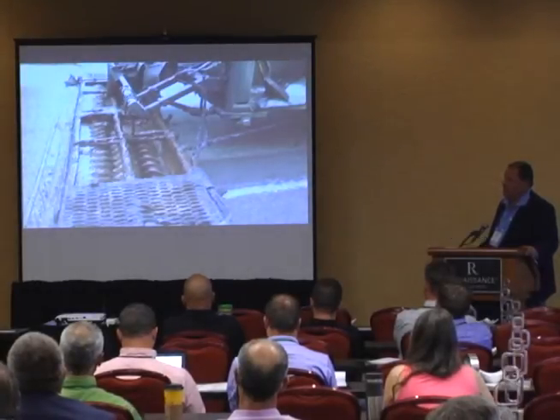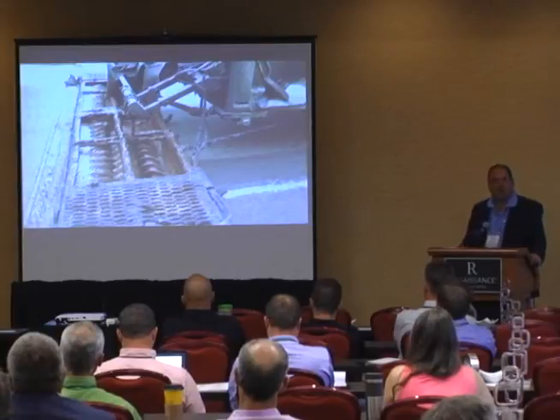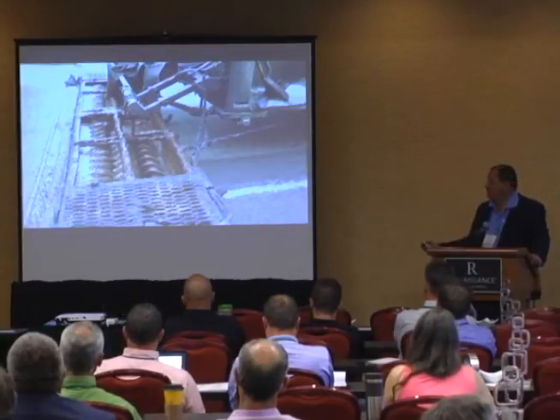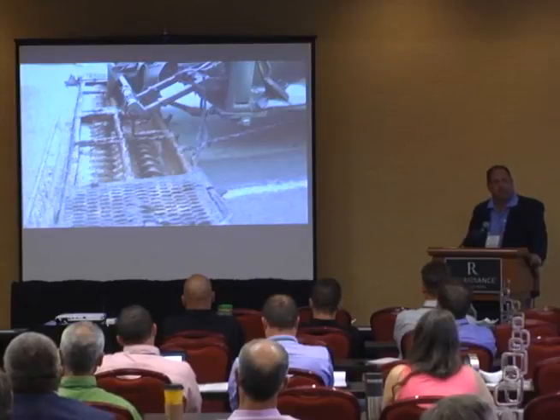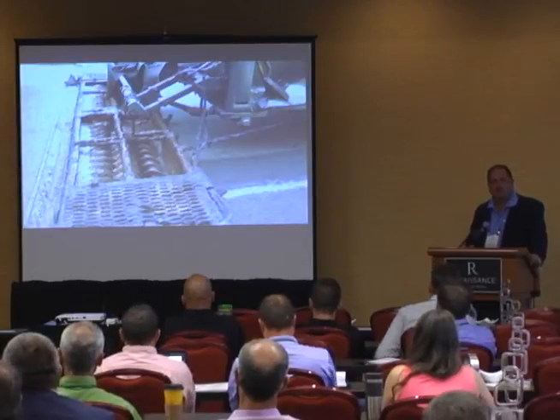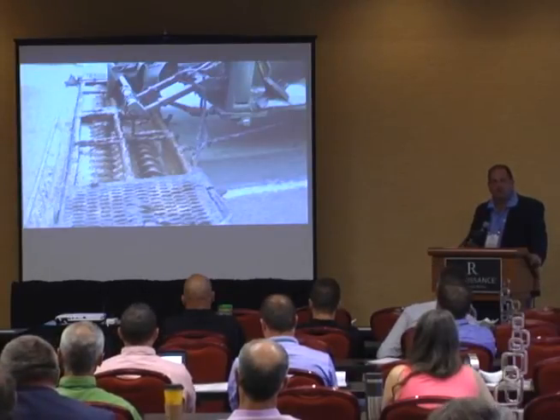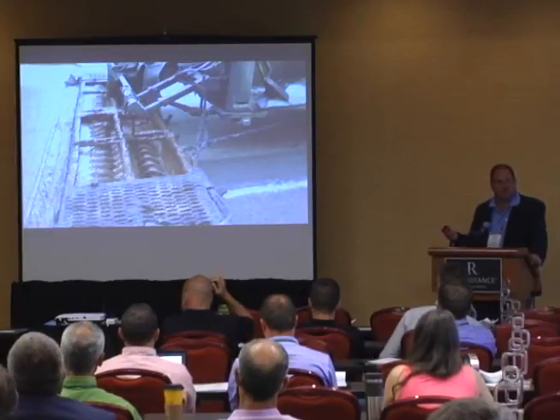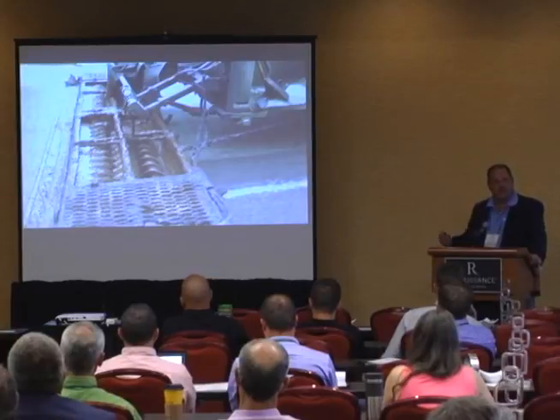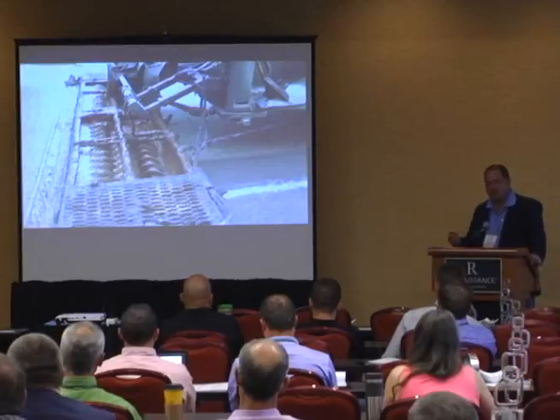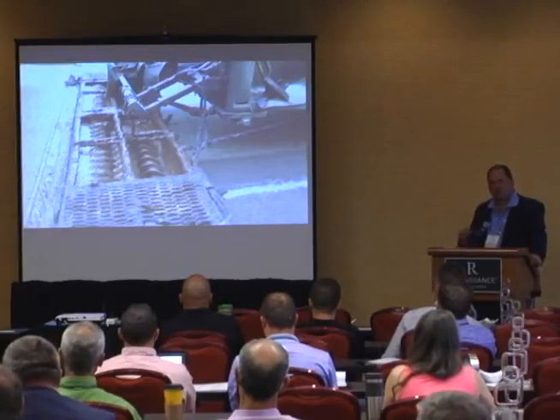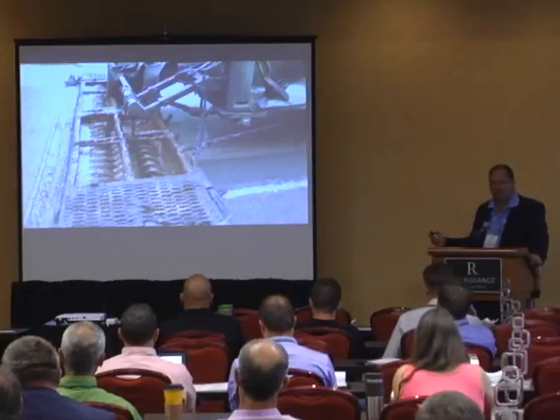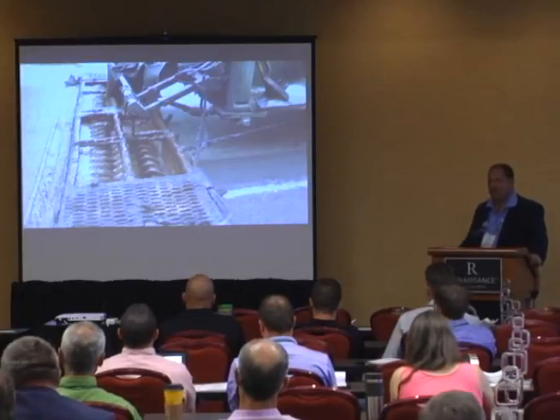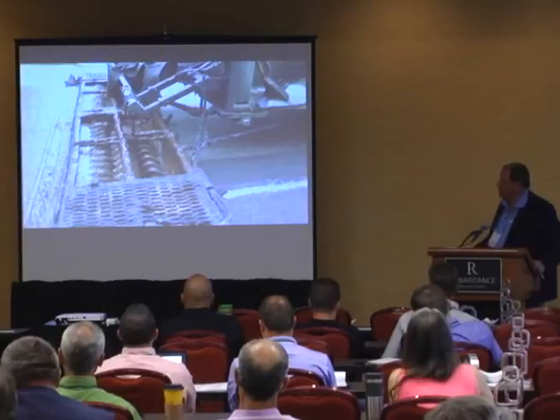One thing that must be done is it has to use an augered box. The viscosity on that material is significantly different than the other microsurfacing and other emulsions, so you have to use an augered box to keep that material moving. The only projects we've seen with difficulty in the learning process were the 4 contractors that we said, please have an augered box, and they didn't show up with an augered box. The augers didn't work. They struggled. It dragged. It built up in the box. So an augered box is key to the success of utilizing these highly modified, high viscosity materials.